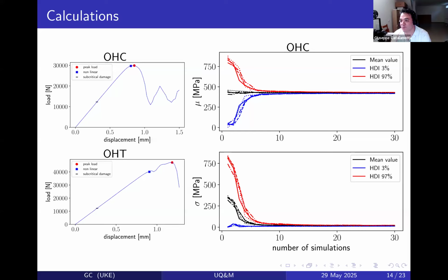Again, around 20 simulations, which is feasible on any PC, and of course on any PC infrastructure, you get this. And this does not depend on the points that you choose to start with. So if you sample and you start with different red crosses, so you run this with different experiments, the values that you get for mu and for sigma, therefore for the expected value and the standard deviation of your quantity of interest, are actually the same. Nothing changed.